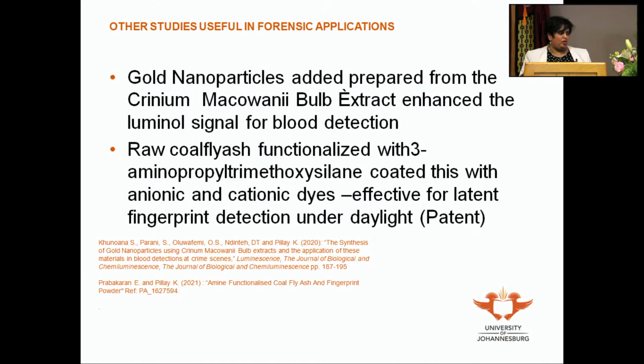We also prepared a bulb extract from a local plant known as Crinium macowanii, and we prepared gold nanoparticles using this bulb extract and added those gold nanoparticles to luminol for blood detection and found that we got an enhanced signal. We also found that the Crinium macowanii bulb extract could potentially mimic luminol in its function of detecting blood.